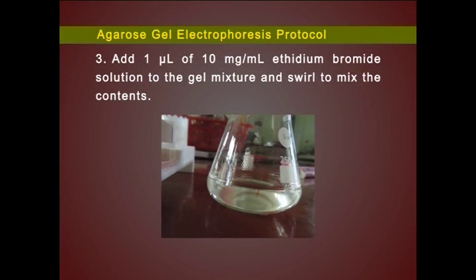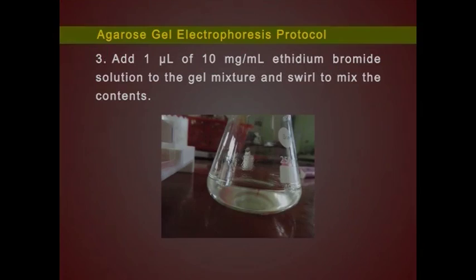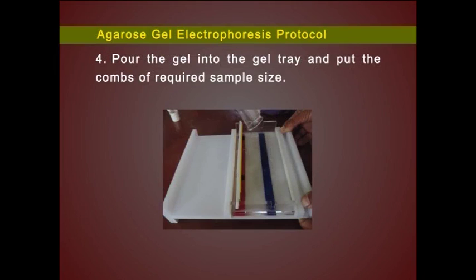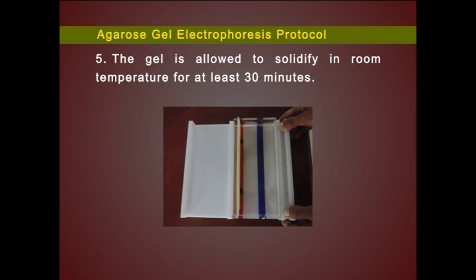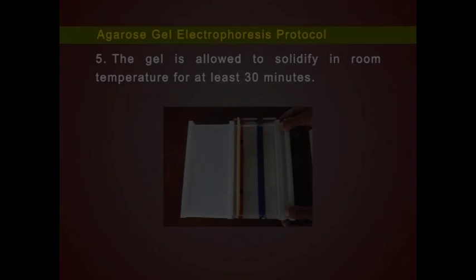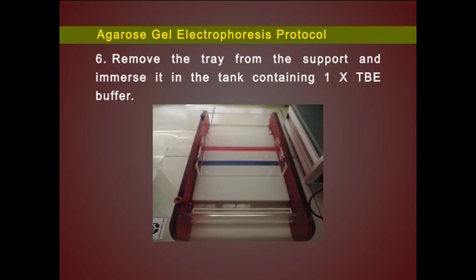Now add 1 microliter of 10 mg per mL ethidium bromide solution to the gel mixture and swirl to mix the contents. Next, pour the gel into the gel tray and put the combs of required sample size. The gel is allowed to solidify at room temperature for at least 30 minutes. Remove the tray from the support and immerse it in the tank containing 1x TBE buffer.